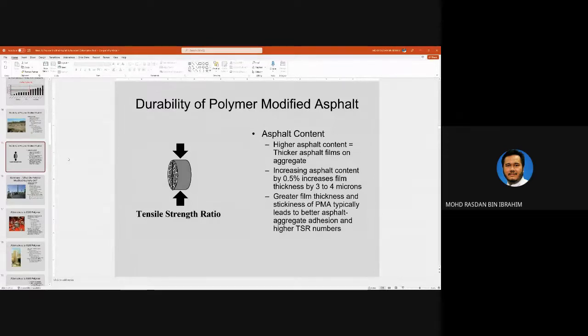Actually, this is another useful feature for asphalt, polymer modified asphalt. So by increasing asphalt content by 0.5%, the binder thickness increases by 3 to 4 microns. So thicker film thickness typically leads to better asphalt aggregate adhesion and higher tensile strength ratio.